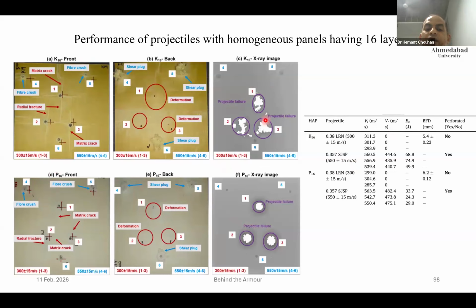So you see, because of fibrillation, this white part is actually the lead core of the projectile. It is non-uniformly damaged. Whereas in case of UHMWP, a petaling phenomenon, a flower formation, will happen because the fibers will stretch. Fibrillation and damage is an uncontrolled, non-uniform kind of phenomenon. Stretching is a uniform phenomenon.